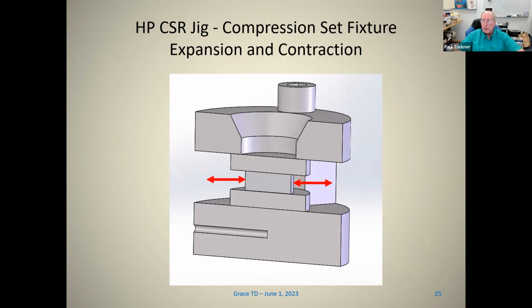But in some cases, during long-term testing such as with certain materials, test specimens begin bonding to the interface at elevated temperatures, so when you cool them back down they can't contract uniformly. They actually get cupped in from the sides and contract axially, which reduces your sealing force. So knowing what's happening in these things is really important.